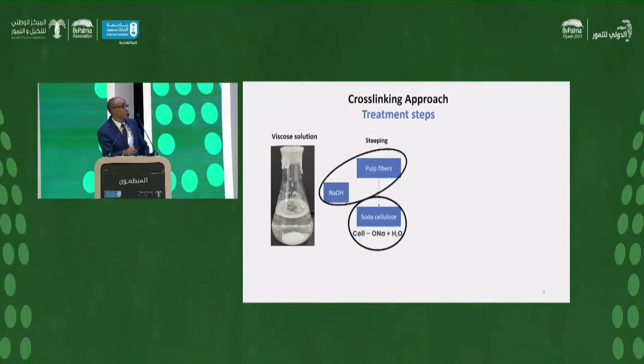The first step is called steeping. We saturate the material with sodium hydroxide. Before, to obtain the pulp of paper, we use the sodium hydroxide to extract the lignin. And now we use it to saturate the material and to obtain a gel configuration or structure of materials, as viscose materials. It's called soda cellulose.